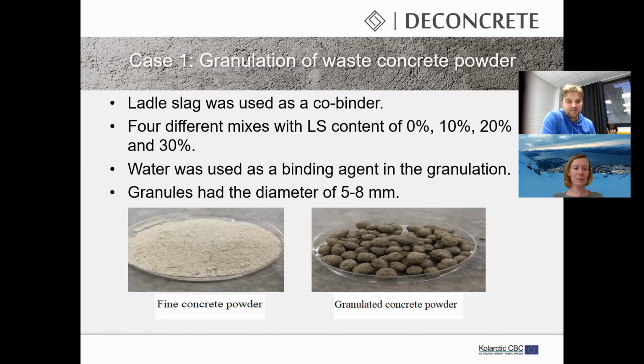And in the granulation process, I used water as the binding agent, and I tried to produce granules with a diameter of 5 to 8 millimeters, because we found some commercial aggregates of similar size, and it was easy to compare them. And in the figures are this concrete powder, and how it looks when you have fresh granules produced from it.